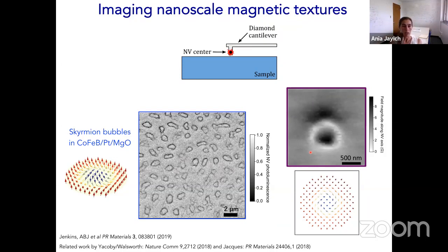Another system that we've looked at recently are these skyrmion bubbles, which, as I mentioned, are these magnetic textures, where here is a schematic of what the spins in a sample look like. In this case, the sample was a thin film magnetic multilayer of a ferromagnet and a material with strong spin orbit coupling. At this interface, one has the possibility of generating these spin textures, which are topologically protected, and they can be quite small. They've become interesting for magnetic storage and magnetic logic, for low power devices, more in the engineering sense.